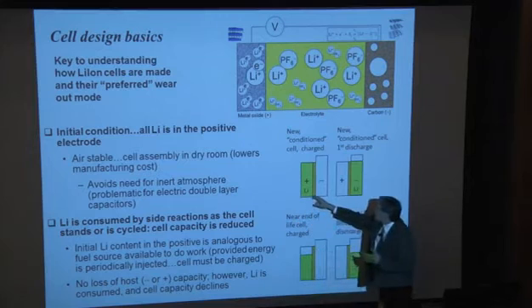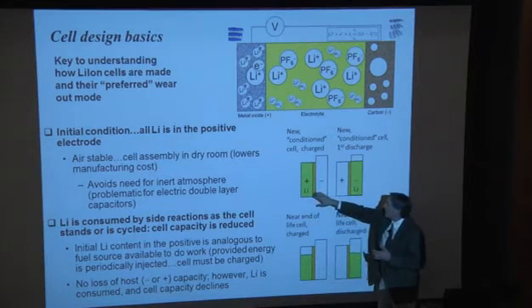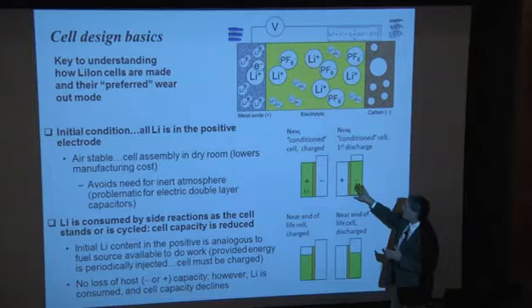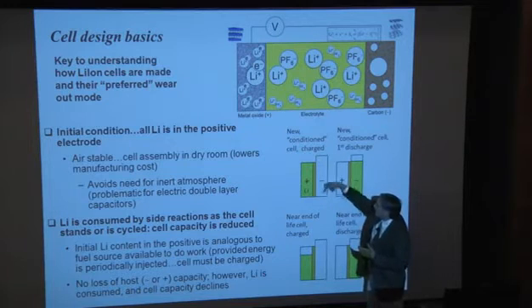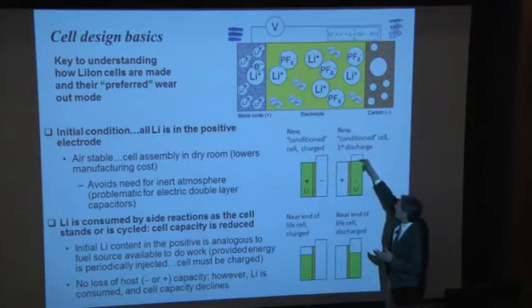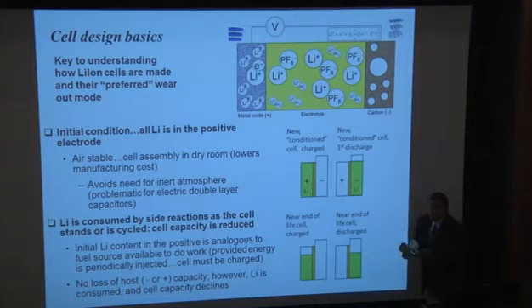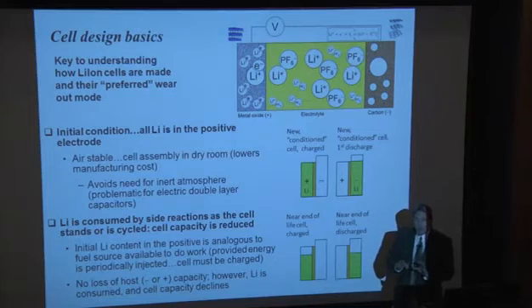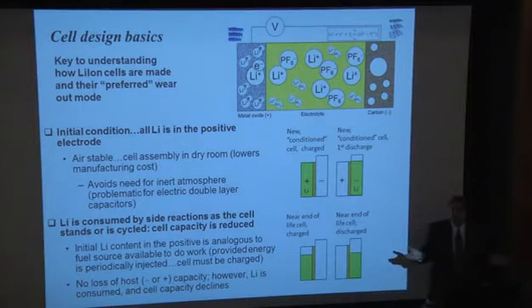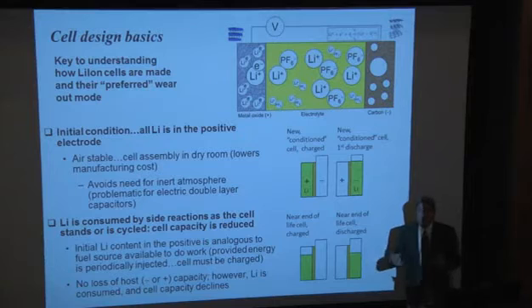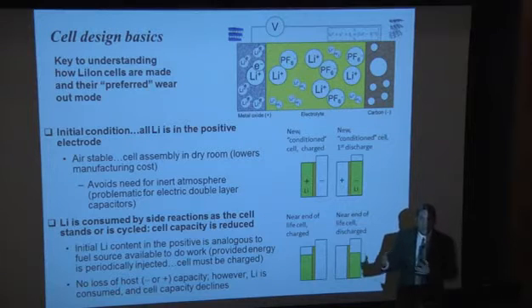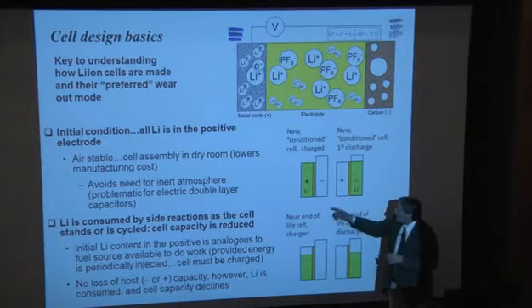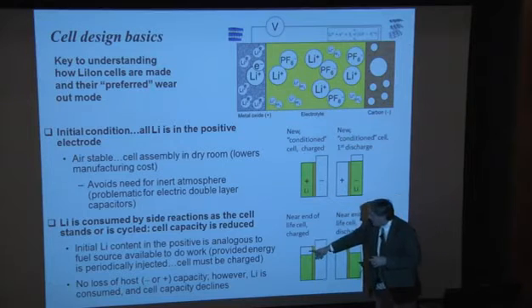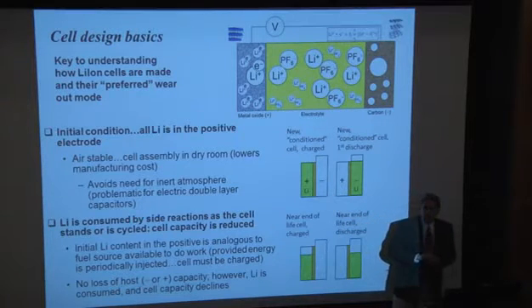Now, when you charge the cell, you put all the lithium from that positive electrode into the negative electrode. And I mentioned you have an excess of negative electrode, so you don't get lithium plating, so you never utilize all the negative electrode. After you cycle the cell, or if you just let it sit, there are degradation reactions, very slow. That's why lithium-ion batteries basically are life of the vehicle. The Chevy Volt, for example, has an 8-year warranty on the battery pack, and it should last much longer than that. But you do get gradual degradation, so that end of life is at about 75 to 80% of initial capacity.